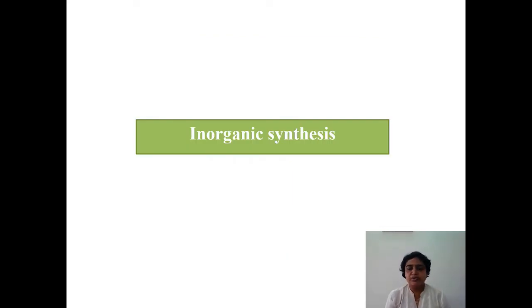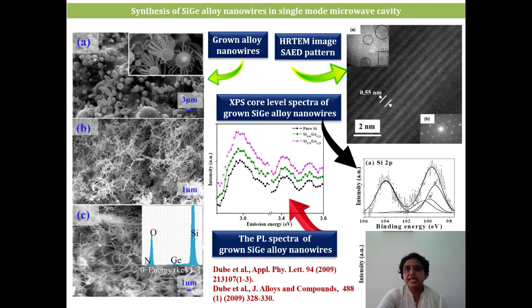So let's come to the inorganic synthesis. The results which I'm going to show are from my PhD work. So we synthesized silicon germanium alloy nanowire with the help of H field processing. Here we used the H field of microwave. So at our workpiece location, the H field was maximum. Just now I have shown the diagram in which E and H field were maximum at different work locations in the cavity. So here we made silicon germanium alloy nanowire, and what we found was that it had a core shell structure.